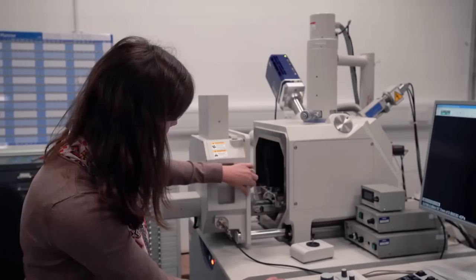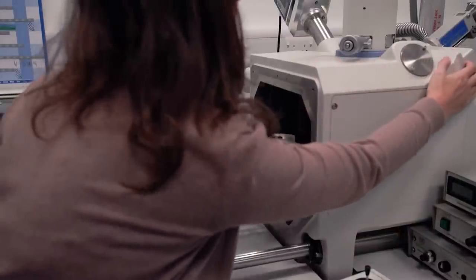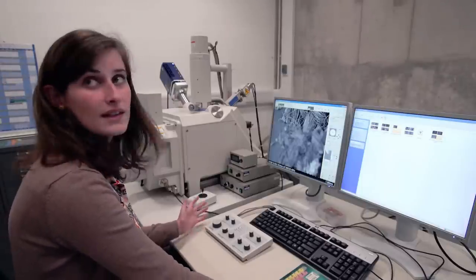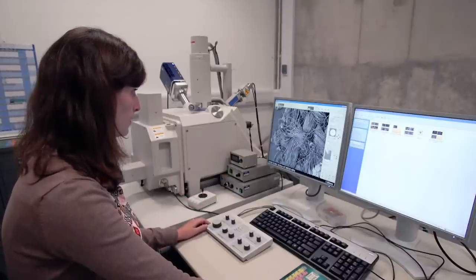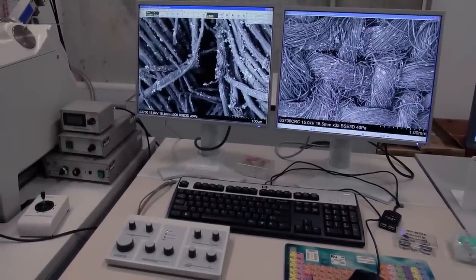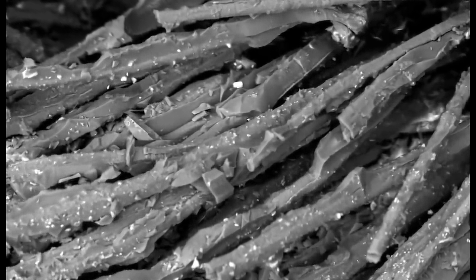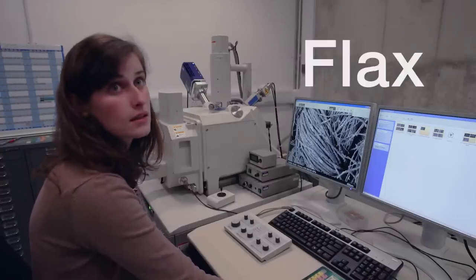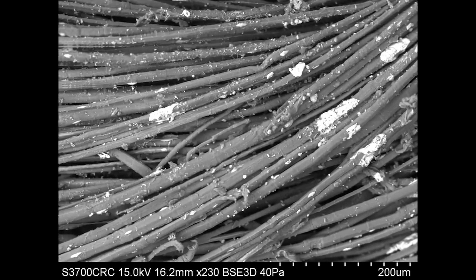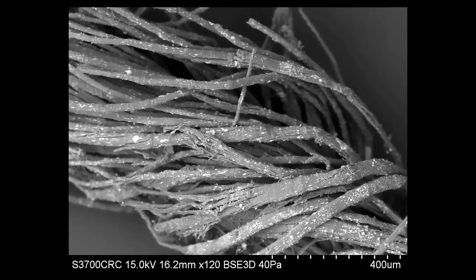The sample slides in and locks in place and then we close up the chamber. All the air is evacuated from the chamber and then we can turn on the electron beam. Here's the first glimpse of the sample — we search the sample looking for areas that will help us find the identifying features. Already we can see dislocations that look a little bit like a knee joint, and that is indicative of flax. The other material visible on the sample is the resin covering the mummy crocodile.